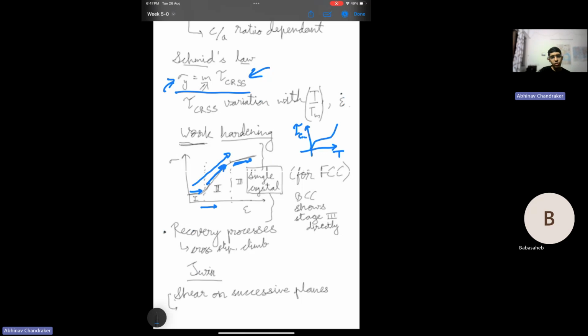Then the dislocations start to cross slip because these obstacles have formed, and that cross slipping also leads to formation of locks or formation of sessile dislocations, because we know the edge components of dislocations cannot cross slip. So those will remain immobile while the screw component will cross slip, and that will lead to both multiplication by the Frank-Read mechanism as well as formation of dislocation tangles and locks and jogs, kinks.